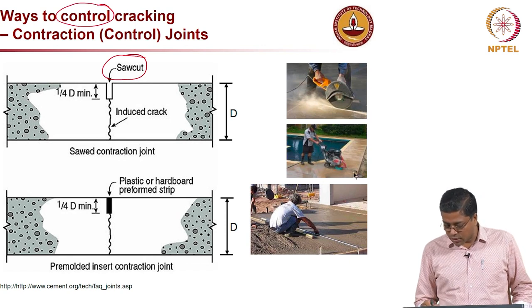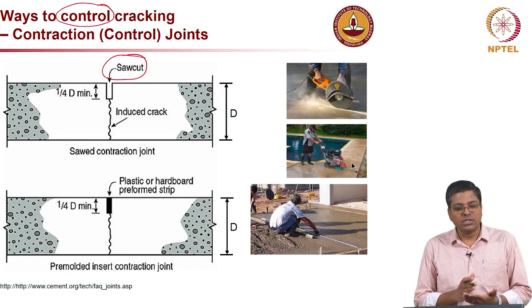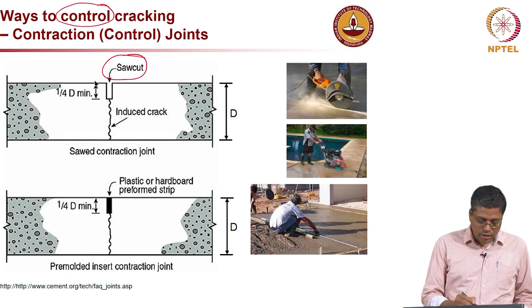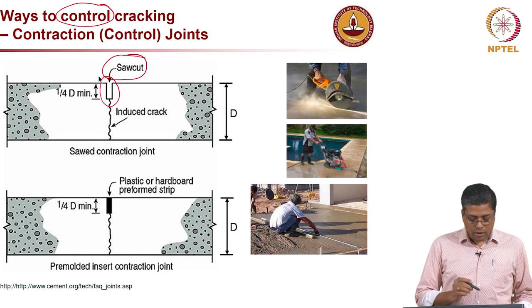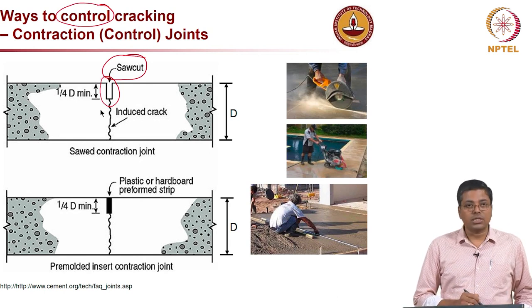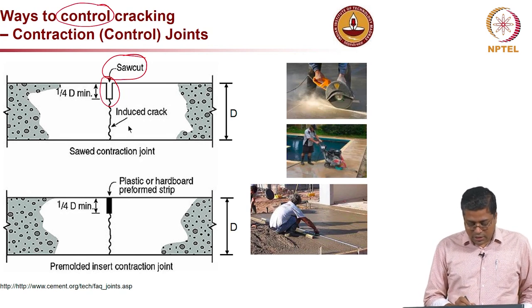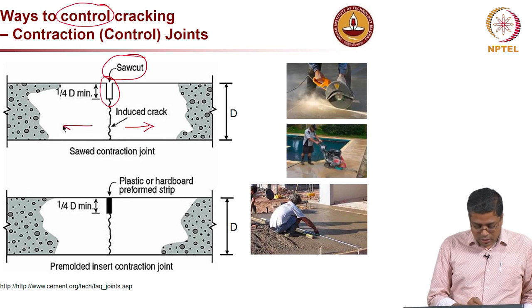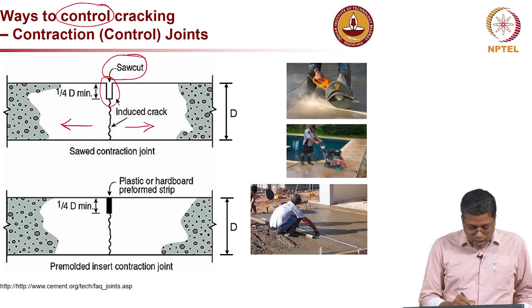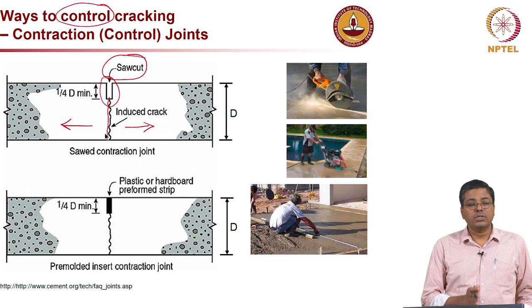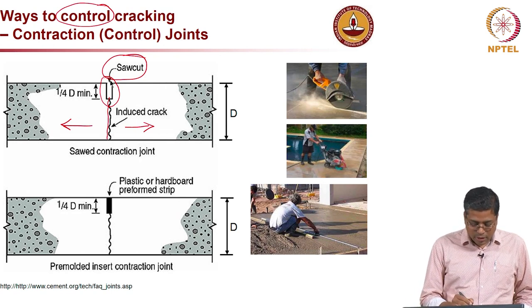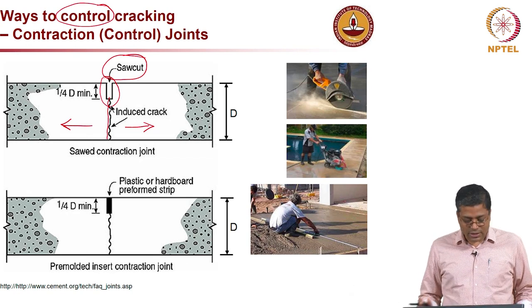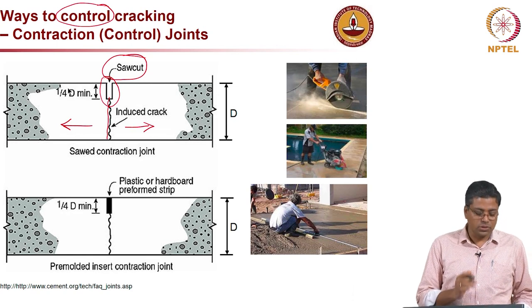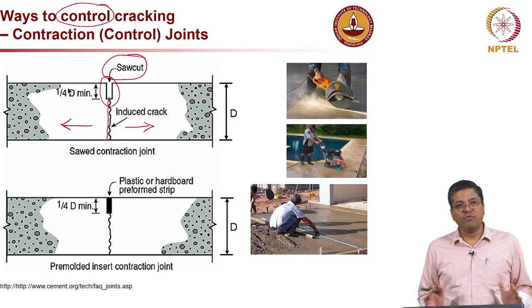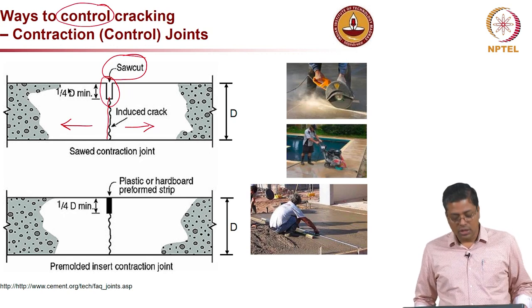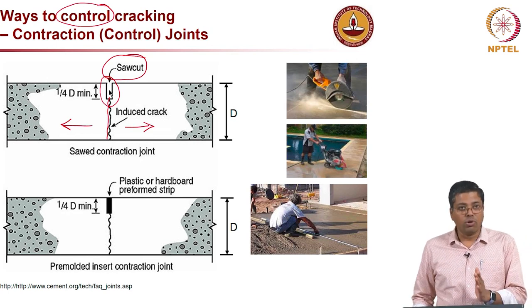You can see people are making saw cuts, or in other words, once the concrete gains sufficient strength, you cut the top surface of the concrete, make a cut like that. Now essentially what you are doing is you are creating a section with smaller area. That means when a particular tensile stress is generated, the concrete will start cracking across that thinner section, right below the saw cut, where the area available is less than the total cross sectional area of the slab. Because of the saw cut, you are reducing the area available. That means for the same force, because the area is less, you will have more stress, and wherever the stress is more, concrete is going to crack there.